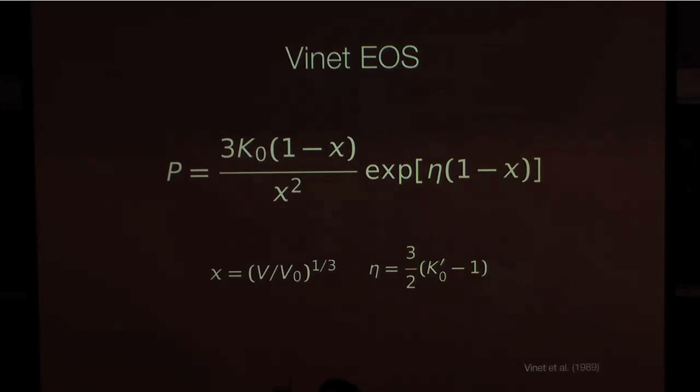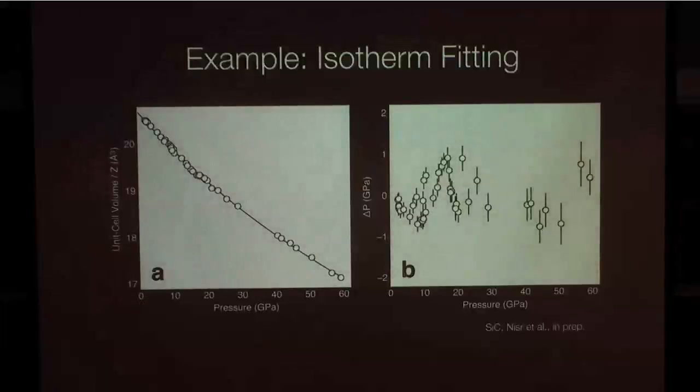So this is the Vinet equation of state. The nice thing about the Vinet equation of state is that you don't have to deal with truncation. It's exact. There's nothing hidden, and it's a 3-parameter equation of state: V0, K0, and K prime. Volume at reference conditions, bulk modulus at reference conditions. What is the third? Pressure derivative of bulk modulus at reference conditions. We need a break, right?